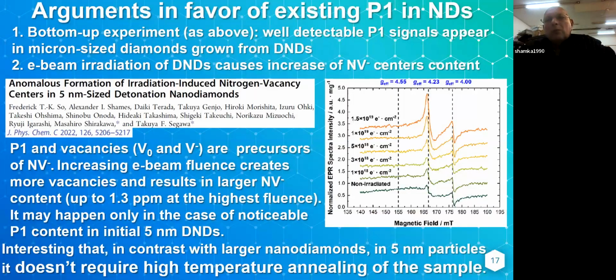Okay, let's go further. There are two main arguments in favor of existing P1 in nanodiamonds. First of all, the bottom-up experiment, as demonstrated above, which says that well-detectable P1 signals appear in micron-sized diamonds grown from detonation nanodiamonds where there were no signals. Another very interesting experiment was done recently in 2022. It's experiments with E-beam irradiation of detonation nanodiamonds. And this experiment causes an increase of NV- center content. Okay?